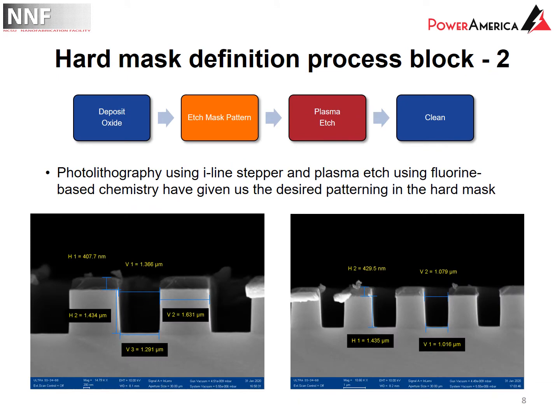Once the oxide has been successfully deposited, the next step is to use photolithography to pattern the wafer with the structure that you want, and then etch the oxide, preferably with 90-degree sidewalls, all the way down until the silicon carbide is exposed. What this will do is allow ion implants into certain sections of the wafer, whereas other sections, the ones that have oxides on top, will be blocked. By using our I-line stepper and plasma etch tools in NNF, we're able to get the desired pattern with very sharp sidewalls and very well-defined features, which will be ideal for ion implantation.